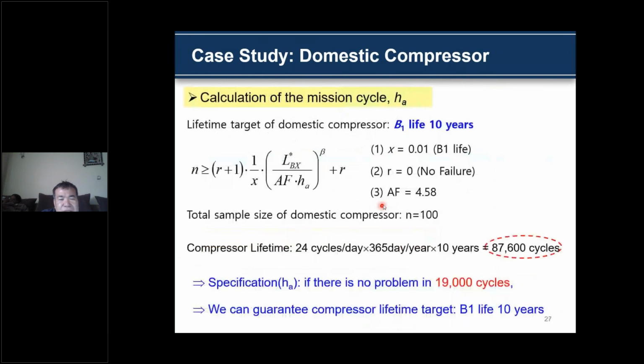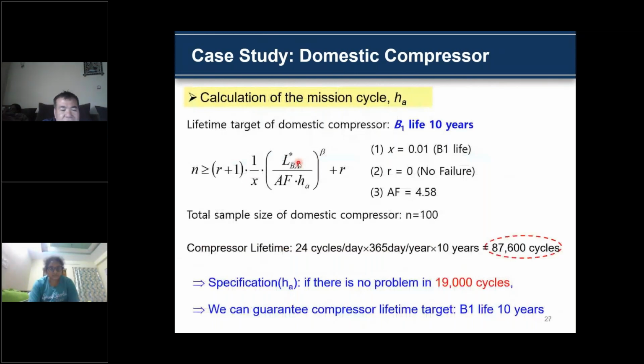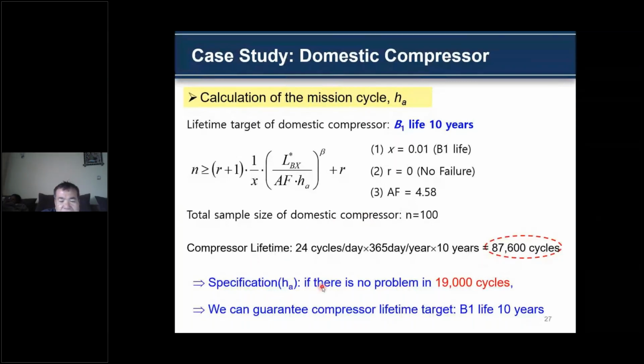For the calculated mission cycle, the life target of a domestic compressor is B1 life 10 years. The acceleration factor is 4.6. The total sample size of domestic compressors is 100. For a compressor life target of 10 years, it is almost 87,000 cycles. If there is no problem at 19,000 cycles, we can guarantee the compressor life target of B1 life 10 years.